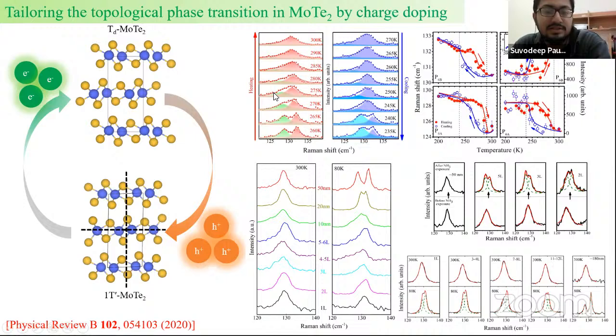As for the experiments that we have performed, we never saw anything of that sort. But the transition to the Td phase has also been reported by other people. For thinner flakes, it becomes a bit tricky. Sometimes we see it stabilizing in one of the two phases, and it becomes difficult to predict which way it would go. There may be phase mixing also, right? It happens that phase mixing is there.